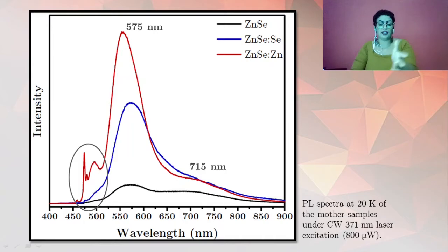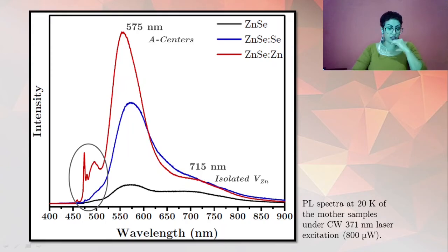the defect-related PL bands in zinc selenide, originated from the radiative recombination between A centers. The existence of these PL bands suggests that defects or impurities are present in the samples, but in very low concentrations, since we cannot observe them by other techniques. In addition, the luminescence band observed at approximately 715 nanometers endorses the suspicion that defects are present in the samples, even at low concentrations, since this band corresponds to the luminescence associated with isolated zinc vacancies.